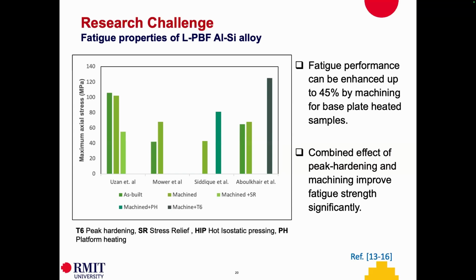Now, if we combine different post-processing treatments, such as peak hardening and machining, we can improve fatigue properties significantly. As you can see here, from all of them, we found if you machine, the maximum axial stress goes up for all of these cases. And if you look at this one, where we machine plus have done peak hardening, you can get significantly higher maximum axial strength.